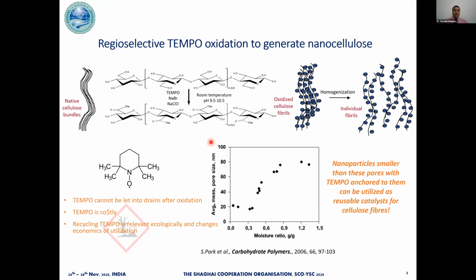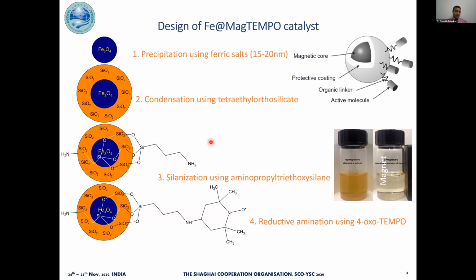I chose to anchor this TEMPO on iron oxide nanoparticles that can be easily separated at the end of the reaction using a magnetic force. However, iron oxide is susceptible to change in its oxidation state due to reaction conditions like high pH, the redox environment, etc. So I coated these nanoparticles in silica or glass and then covalently anchored TEMPO by consecutive silanization and reductive amination steps.